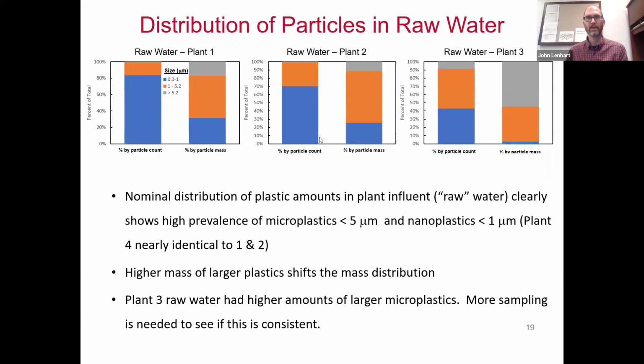Looking a little bit more closely, comparing the concentrations in terms of mass and particle concentrations for the plants. I should note that plant 1, plant 2, and plant 4 had very similar results, so it's only showing plant 1 and plant 2. And then plant 3 had some different results, so that's why it's shown here as well. Again, this is percent of the total plastics, representing it as particle count versus particle mass. Colors refer to different sizes. The gray is our particles that are greater than 5.2 microns. The orange are the particles between 1 and 5 microns. And the blue, those are our true nanoparticles.